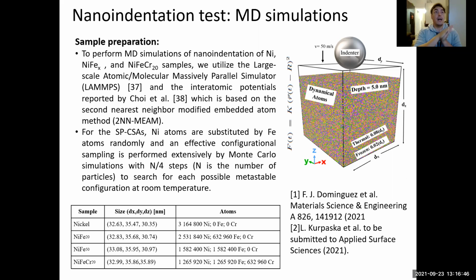So we're really sure, and I also use these interatomic potentials to compute and verify by myself, of course, the elastic constants of these materials, the stacking fault energy, and the surface energy. I have a good agreement with the reported paper by Choi et al. And also with experimental data. So these potentials, I trust them.